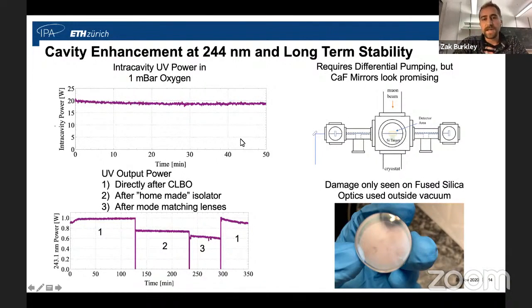Now, while this is very stable, what actually degrades over time is the optics leading up to the vacuum cavity, even though there's less power on these and they're not in vacuum. So what I have here a plot of is our UV power after our CLBO crystal. We have 1 watt stable for several hours. Then we have to go through some isolation optics before we go into our linear cavity. We take a big hit in our power.